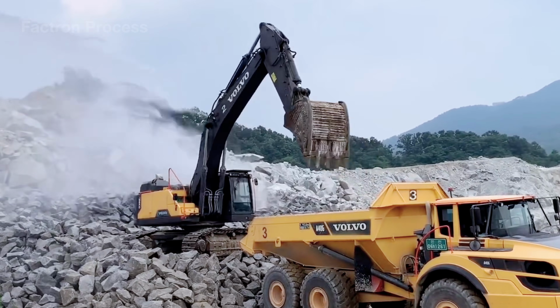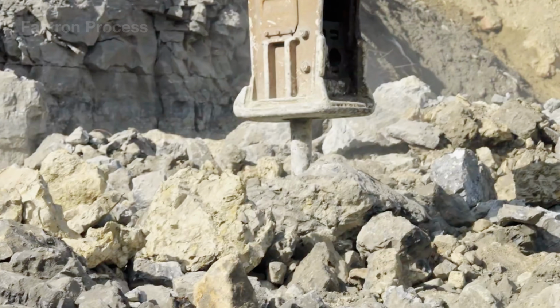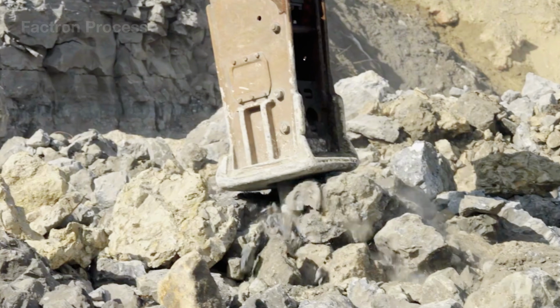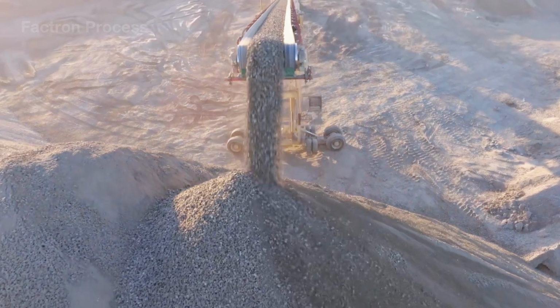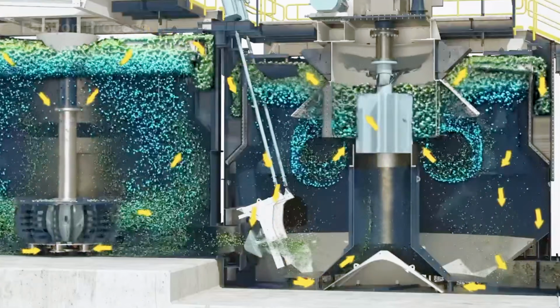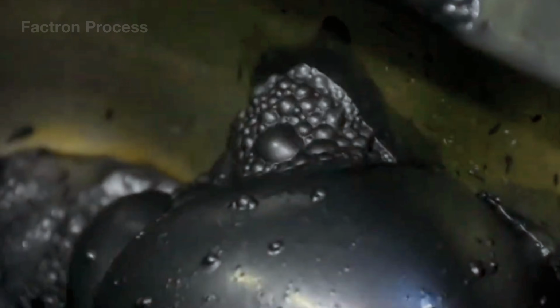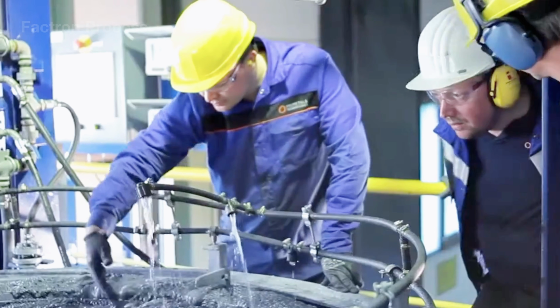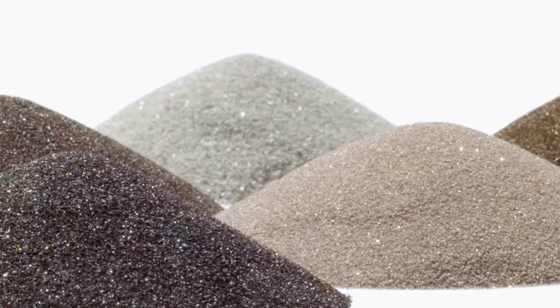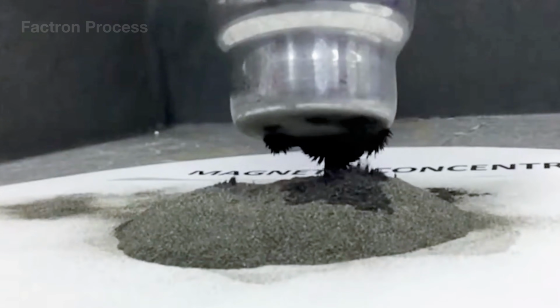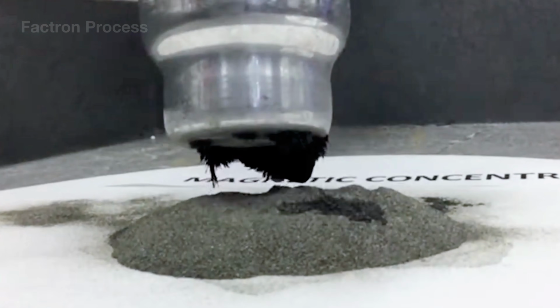Hidden inside every small magnet is a manufacturing chain that demands extremely high precision. Even a minor error in alloy composition, particle size, crystal orientation, or sintering temperature can reduce magnetic strength, heat resistance, and service life. Factories must maintain extremely low oxygen levels, apply pressures of hundreds of megapascals, use temperatures reaching thousands of degrees, and rely on inspection systems capable of detecting extremely small defects.